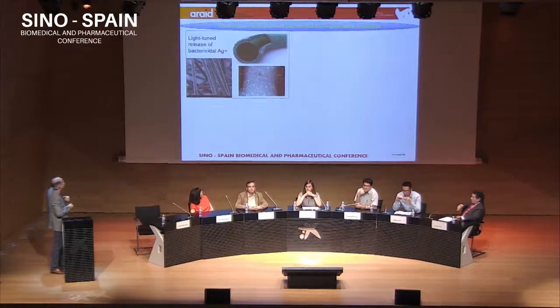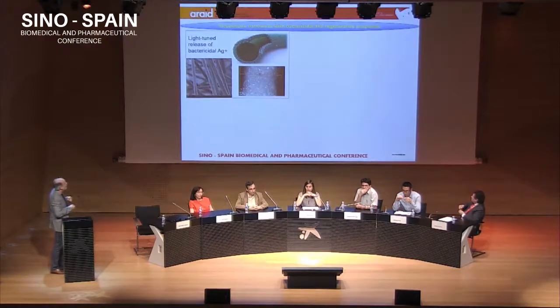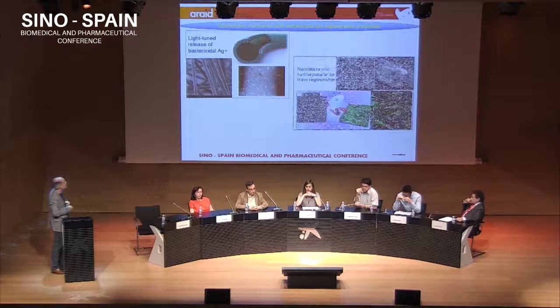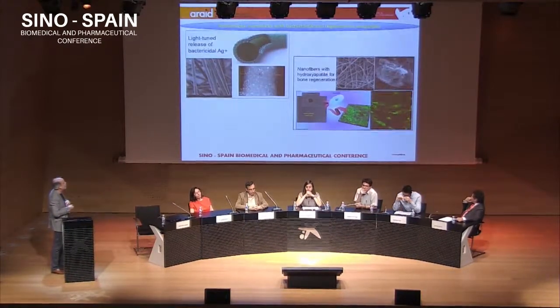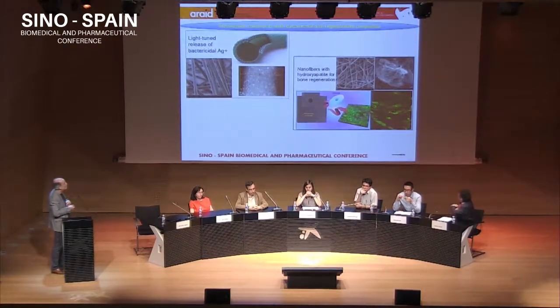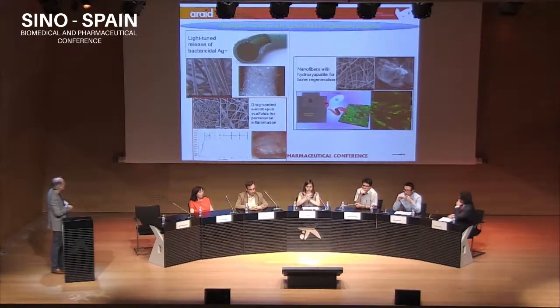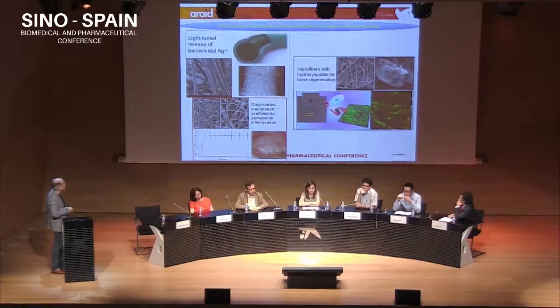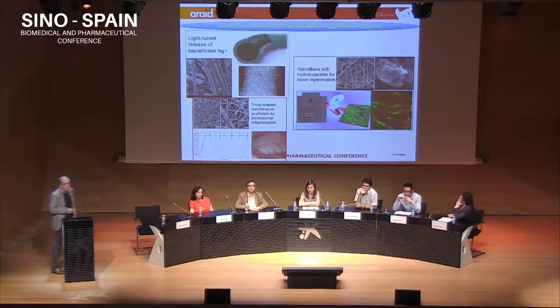So in that case, for instance, these are the nanowires, we have put silver nanoparticles, and by a light irradiation procedure that we have controlled, we can control the release of the silver and the bacteria-killing capacity of these nanowires. Another example: these are nanofibers loaded with hydroxyapatite for bone regeneration, plus growth factor, so this can be loaded with osteoblasts and regenerate bone. And another example of drug-loaded scaffolds, for periodontal inflammation. In that case, it contains both antibiotic and anti-inflammatory drugs, and this is the release profile.